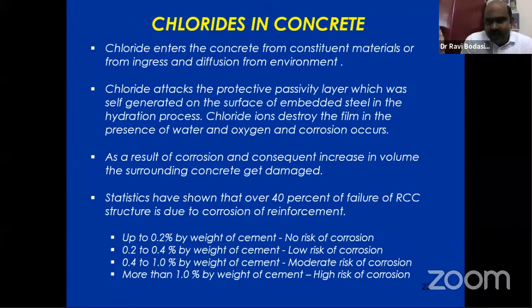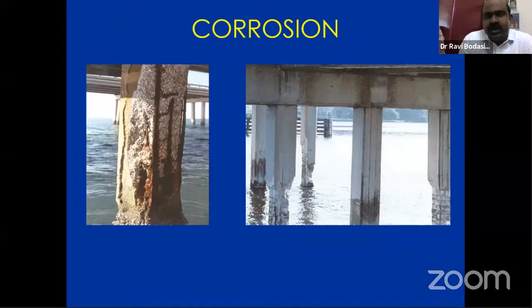So these are the limits that have been given: up to 0.2% chlorides by weight of cement, no risk of corrosion; 0.2 to 0.4%, low risk; 0.4 to 1% by weight of cement, moderate risk. If the chlorides are more than 1% by weight of cement in a mix design, say for example you are using 300 kg of cement, then this gives a high risk of corrosion. Once corrosion starts, it is nothing but a cancer to the concrete.